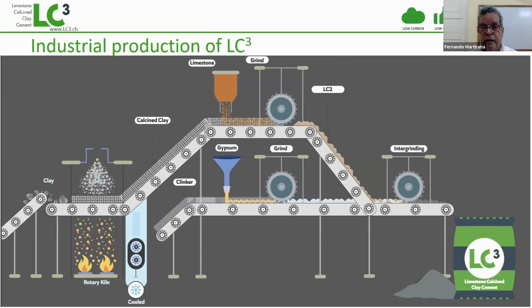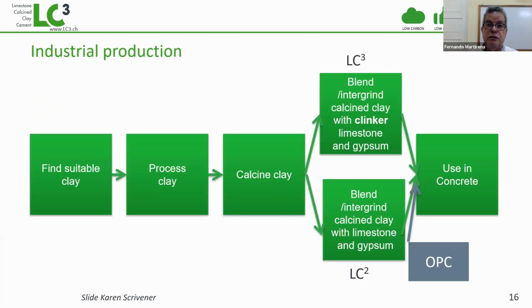So basically you take suitable clay, you fire it at 800 degrees Celsius, then you can either blend it with clinker and gypsum and limestone and make the cement itself, or you can produce a mineral addition, we call it LC2, by grinding it, blending it with limestone and grinding it. Those are very interesting choices for production. Of course, you need to have this suitable clay. You need to process this clay, where you have to go to the brick industry to get expertise. And then you calcine the clay and then you do the whole thing of blending until you use it in